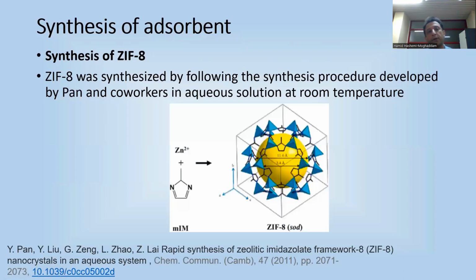For synthesis, the first step is preparation of this nano-adsorbent. First we must use a core for this, and the selected core is ZIF-8 because of its high porosity. For synthesis, the procedure developed by Pan and co-workers in aqueous solution at room temperature was used. This figure shows the structure of this. It contains zinc and methylimidazole.